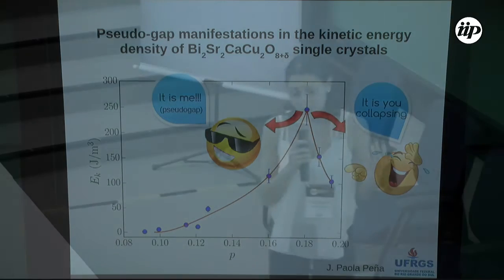But actually, we think that this peak is because of the collapsing of the pseudogap phase. And this result would be consistent with the existence of Van Hove singularity in the density of states, and with a quantum critical point at this value of p around 0.18. We are working on these results already. This is not a finished work, so we are open to discussions and new ideas. That's because I am presenting a poster here. I hope you remember me, because I don't remember the number of the poster, so I will be around, so we can speak there.